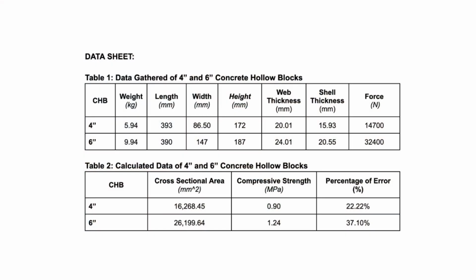Compressive strength testing assesses the amount of compression that a concrete hollow block can withstand. Dimensions play a significant role in meeting physical requirements. Table 1 indicates that the 4 inches CHB has a shell thickness of 15.93 millimeters, which does not meet the ASTM C90-23 standard of 19 millimeters.